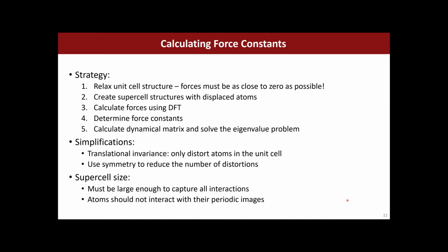So how big do these supercells need to be? There's unfortunately not one answer to fit everything. Essentially, the answer is big enough, which is not a satisfactory answer, but it is unfortunately the answer. It needs to be big enough to capture all the interactions. At some point, your force constants will go to zero. It is unfortunately not always easy to see a priori what that cutoff distance is. And atoms, in the end, should not interact with their periodic images.